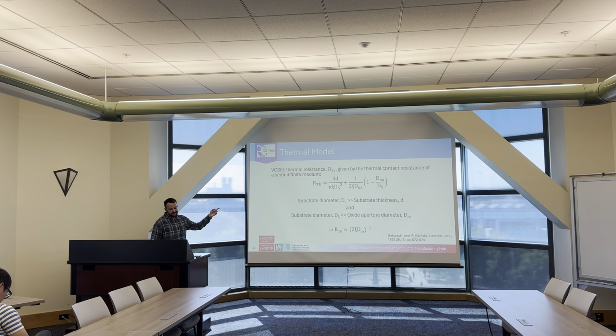We can use this analytic expression for the thermal resistance to fit to the data. So that's the full expression, but in our case we're measuring it on wafer, so the substrate diameter is huge compared to the substrate thickness. So the first term on the right hand side disappears, and as well the substrate diameter is a lot larger than the oxide aperture diameter, so this bracket term goes to 1. So then we're just left with this expression, which we can fit to the data to extract the thermal conductivity.